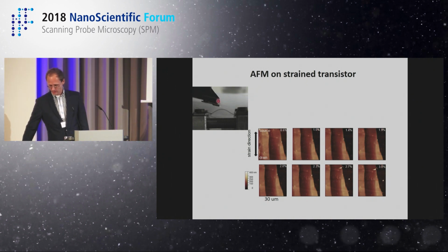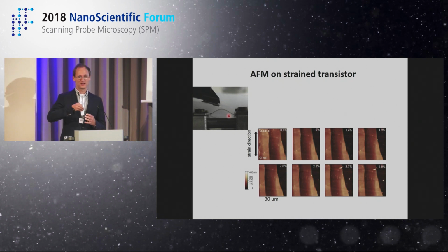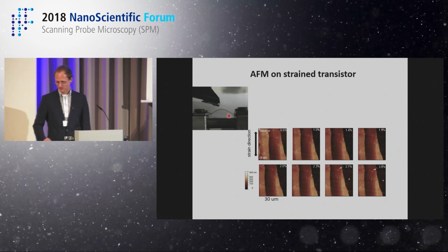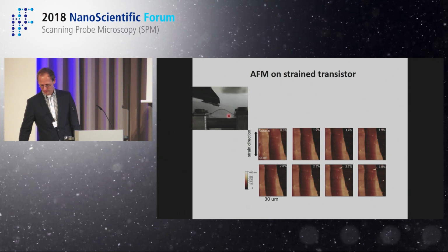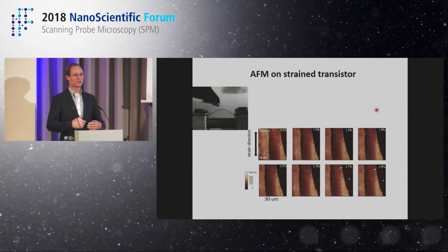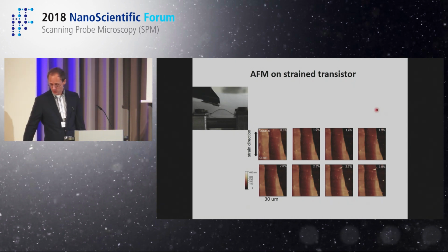This is the experiment: you can stretch a device and at the same time do an AFM experiment. I wasn't so sure in the beginning whether that's actually possible, but it is, so that's nice. And you get morphology images that are shown here, but they do not really contain information. I do not see a large opening of a crack, right? Because at the end I have a small percentage of strain. If there are some nano cracks, I would really have to go into detail and look everywhere in order to find them, which would take quite a long time.